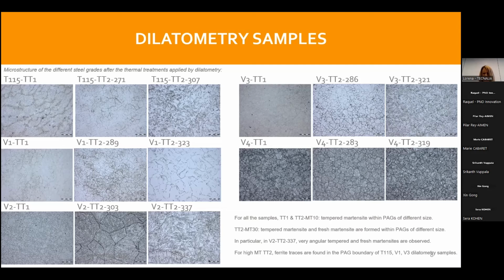And in the case of samples T115, V1, and V3, we can observe ferrite traces decorating the prior austenite grain boundary of the microstructures when applying the high MT thermal treatment 2. So these are the main aspects to highlight at microstructural level.